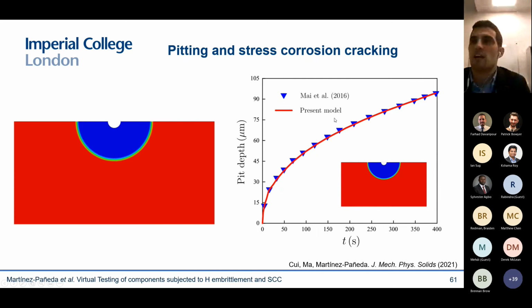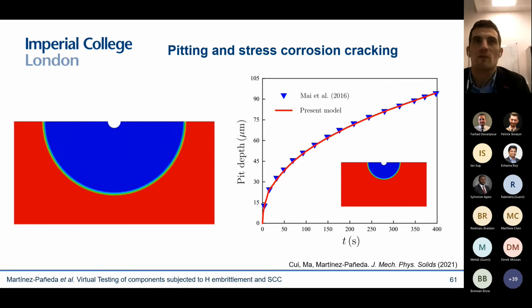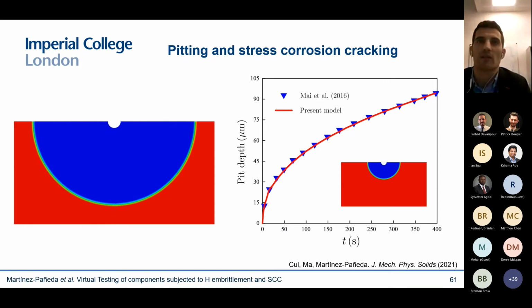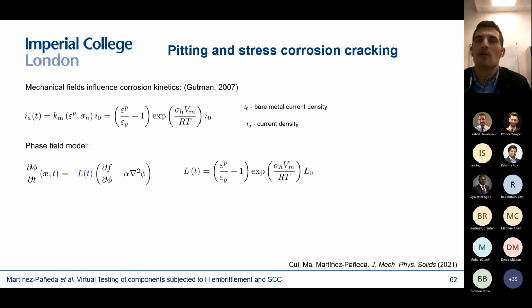But let me just show you a few examples. This is a pit, for example, growing in a rather uniform way. And you can see that it agrees very well with predictions from the literature. And what I want to emphasize a bit more is that what we have done is to extend this theory to incorporate also mechanical effects. And there are two kinds of mechanical effects that we have incorporated. The first one is that, as argued by Gutman and many others, the corrosion current density is going to be related to the mechanical fields. So it's going to be enhanced by mechanical fields.